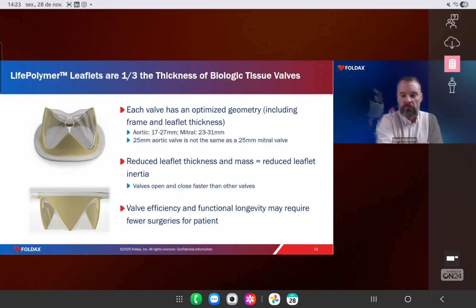You have a different pressure gradient for each environment, aortic versus mitral. Also with this polymer, we can get it relatively thin, and reducing the thickness of the leaflet reduces the mass and therefore reduces the inertia. And so the valve leaflets can open and close faster than other valves.